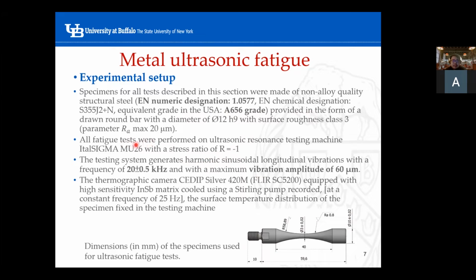The fatigue tests are performed on the ultrasonic resonance test machine with a stress ratio of -1. The frequency is around 20 kHz, and we apply a vibration amplitude of 60 micrometers.